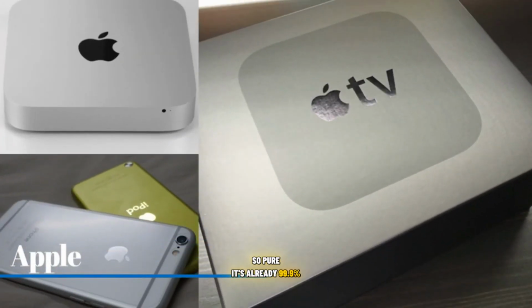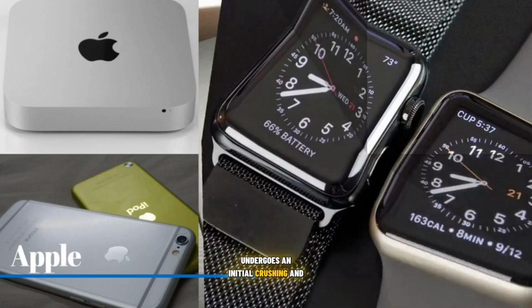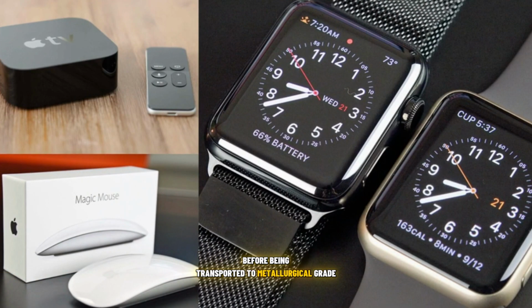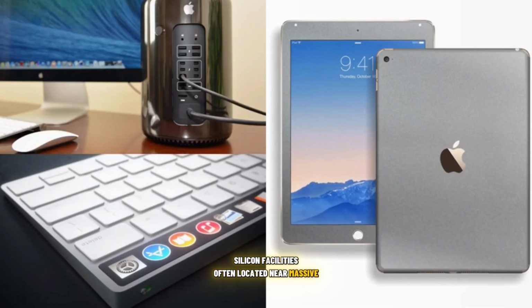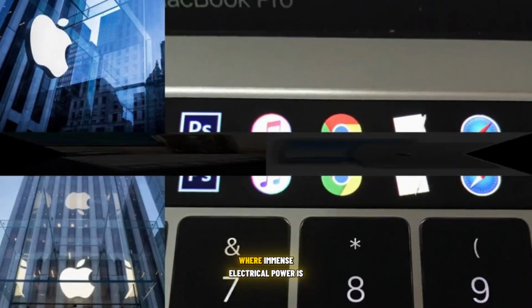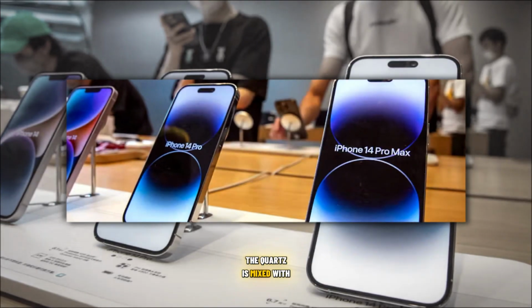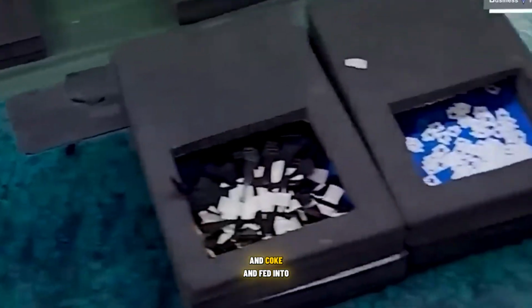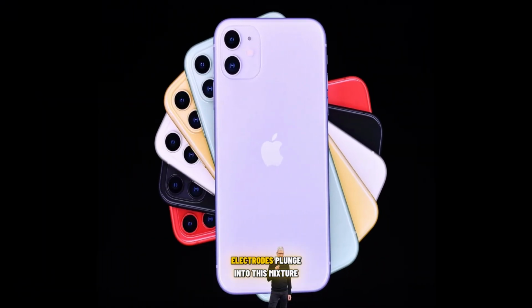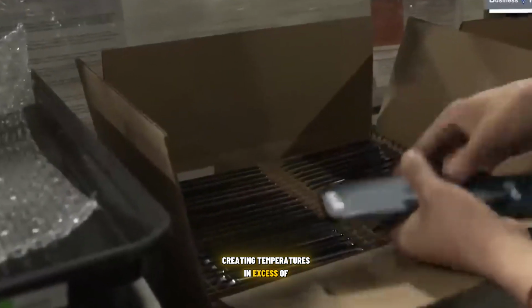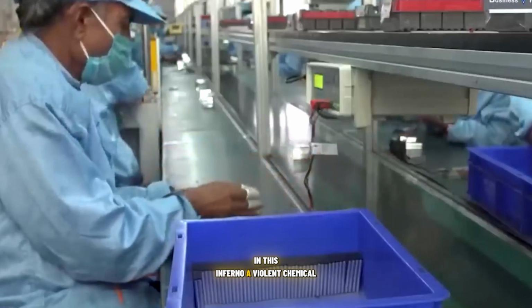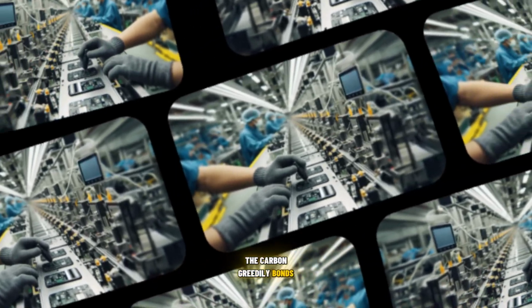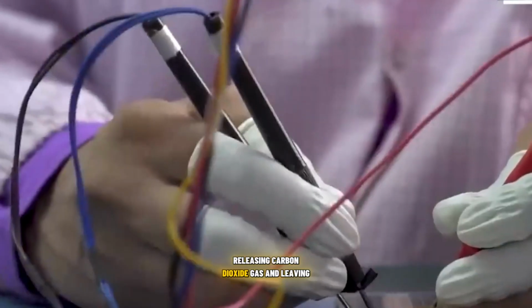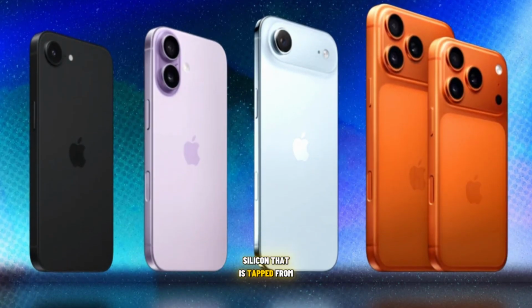it's already 99.9% SiO2. This raw quartz undergoes an initial crushing and washing process before being transported to metallurgical-grade silicon facilities, often located near massive hydroelectric dams in the Pacific Northwest, where immense electrical power is readily available. Inside these vast, humming industrial halls, the quartz is mixed with carbon sources like wood chips, coal, and coke, and fed into a submerged arc electric furnace. Electrodes plunge into this mixture, creating extreme temperatures. In this inferno, a violent chemical reaction occurs. The carbon greedily bonds with the oxygen in the quartz, releasing carbon dioxide gas and leaving behind molten 98-99% pure metallurgical grade silicon that is tapped from the bottom of the furnace.